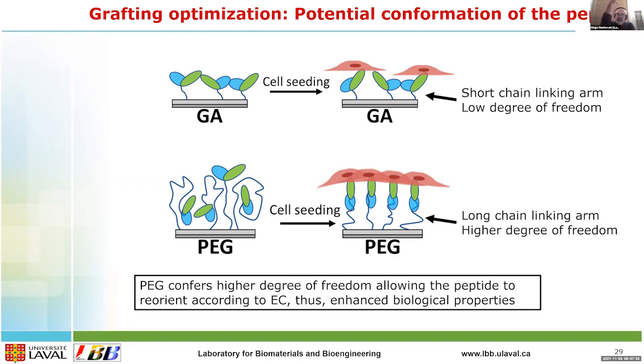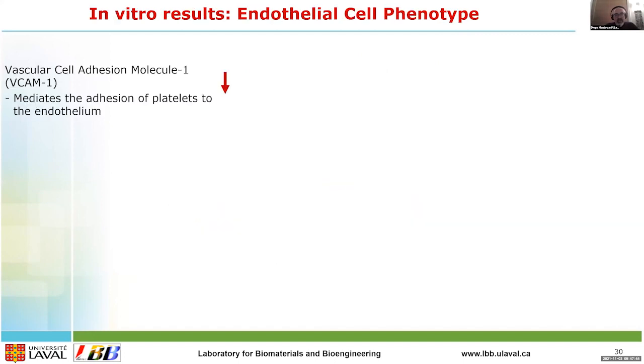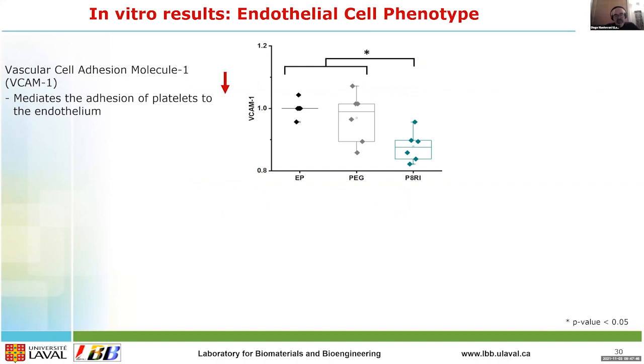Theoretically, I really imagine that the PEG is blocked on the surface, and the bioactive molecule is in my hands, and the PEG allows, like a sort of algae in the ocean, a sort of mobility of your peptide. For the in vitro results, we checked the endothelial cell phenotype, and we see that the vascular cell adhesion molecule, VCAM1, mediates the adhesion of platelets to the endothelium.